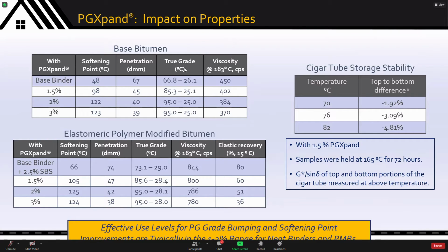What you will notice, this is for folks who are used to PG grades, you will see that it does not change the low temperature grade while it is boosting the high temperature grade. While the softening point is going up, the low temperature properties are maintained. And again, while the high temperature properties are improving, you can see an attendant reduction in viscosity of your bitumen, anywhere from 5 to 15%. This is in the case of a neat binder.